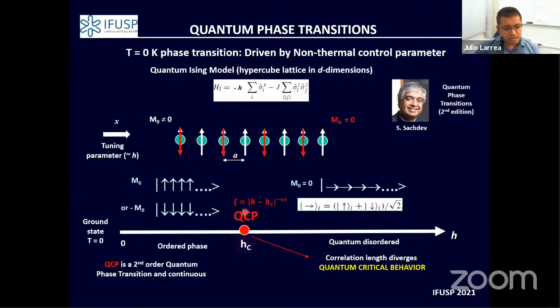When the phase transition at zero temperature is continuous, it's called a quantum critical point. This quantum critical point is characterized by the divergence of the correlation lengths as the system approaches it. So in this case, the system given by a simple spin model shows a continuous transition, and the correlation lengths diverge, showing quantum critical behavior.